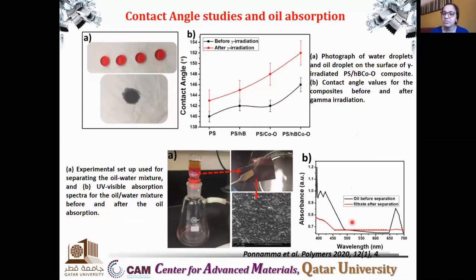And this is the oil before separation and the filtrate after separation, the UV visible absorption. So the question is, how can you ensure that your oil molecules are being absorbed or filtered from your oil water emulsion? There are different methods, of which one method is the UV visible. You take a UV spectrum. If there are oil molecules, you will get some peaks for the oil molecules. And if there are no oil molecules after the filtration, you cannot see any peak. So this will be like a line. And this is the SEM image after the oil being absorbed. It also shows that there is no fiber. You cannot see the fiber because the fibers are immersed in oil. Fibers are completely absorbing the oil.